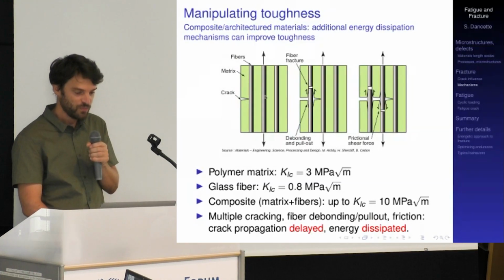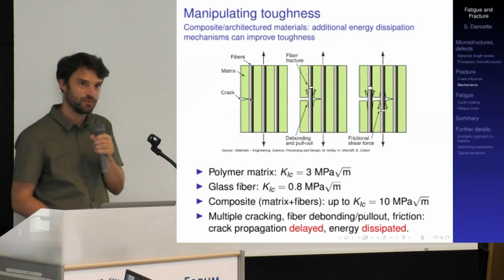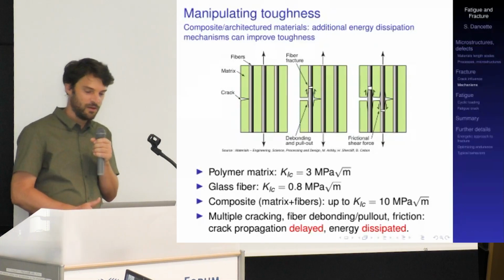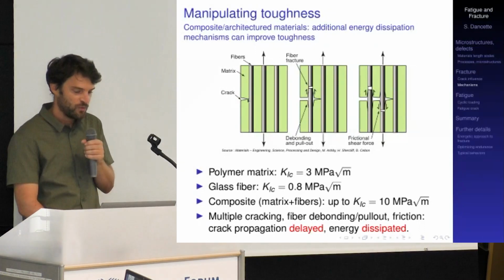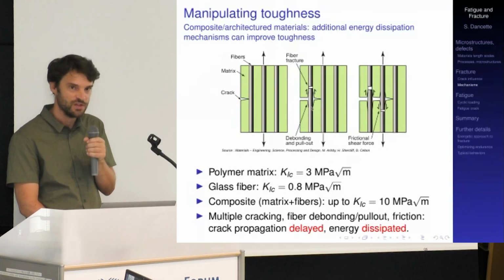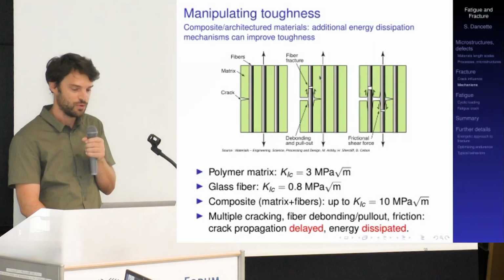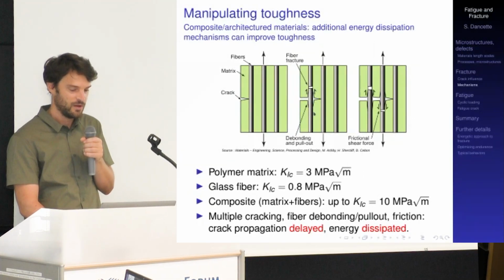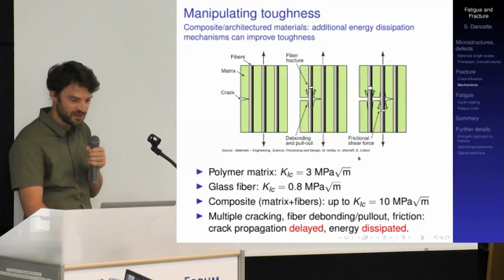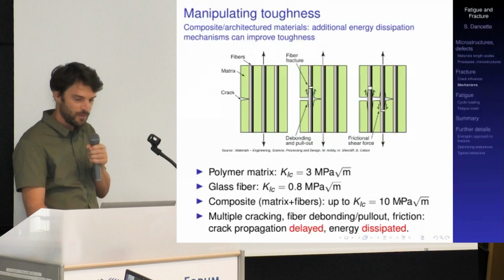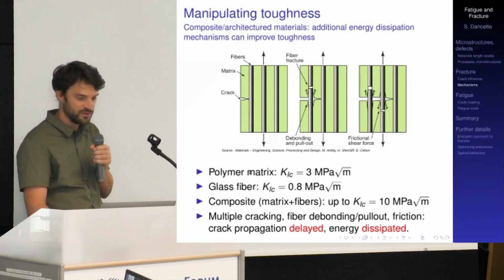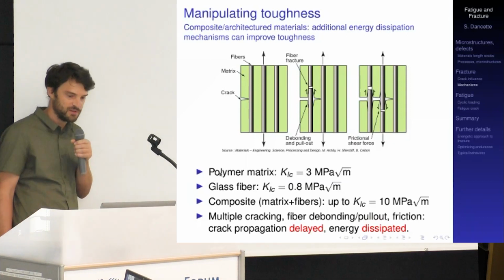So because not only of the individual phases, but of the way they are interconnected together, and in fact they adhere to each other. When a crack tends to propagate in such kind of composite materials, the crack tends to be deviated and to initiate additional fracture mechanisms, for example, in the case of a fiber fracture here. And then afterwards, there will also be some energy dissipated in the debonding and in the pull-out of the fiber itself. And all of these dissipation mechanisms tend to produce a fracture toughness that is, in the end, much higher in the composite material compared to the individual material matrices.